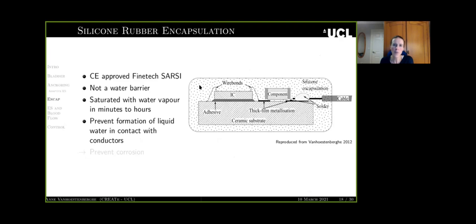If you look at this paper, the dotted area here represents the silicone rubber. And what it shows you is that if silicone rubber covers every surface, in particular every conductive surface, then no liquid water can form. And if there is no liquid water, there cannot be conduction between two conductors, and there cannot be corrosion. And this is, in a nutshell, the principle by which silicone rubber encapsulation works.